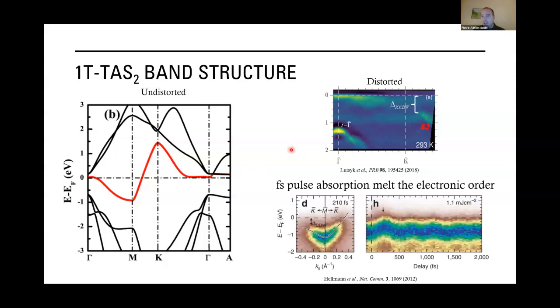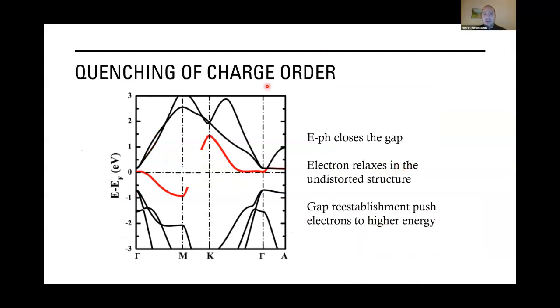And so what has been shown with time-resolved ARPES is that when a femtosecond pulse is absorbed, this gap is going to close due to electron-phonon coupling. So on a time scale of the electron-phonon coupling, like we have seen, a few hundred femtoseconds in this material, we are going to close this gap. So if we look at the dynamic that we expect when we photoexcite electrons, we are going to have electron relaxation through electron-phonon coupling and the closing of the gap.